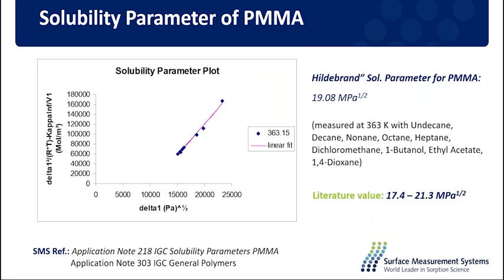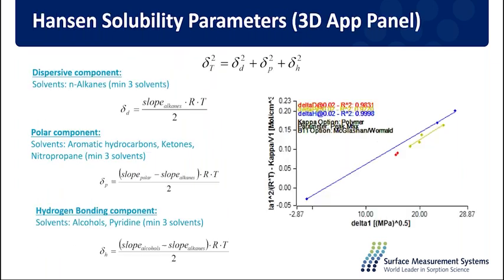We measured this Hildebrand solubility parameter of a PMMA sample. You can see the results on this slide. We have an application note about it. It's available on our website. What we measured, 19.08 megapascal root square, is very close to the literature values we found. And those literature values were mainly calculated values based on group contribution methods. So the difference is very normal.